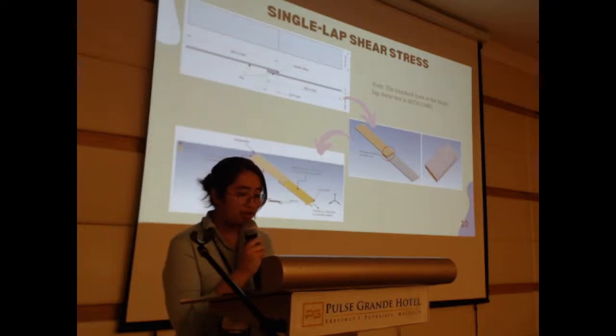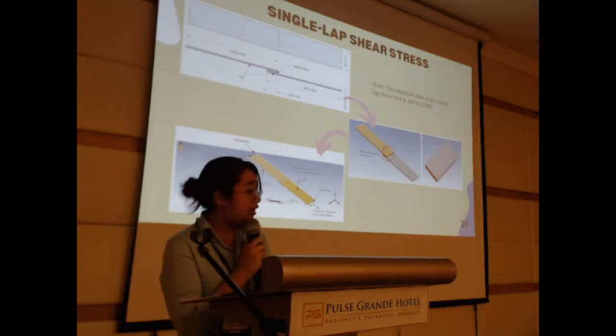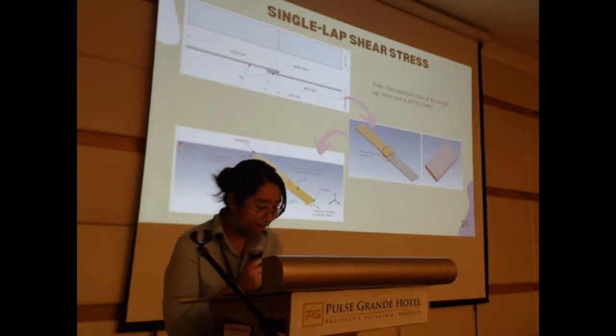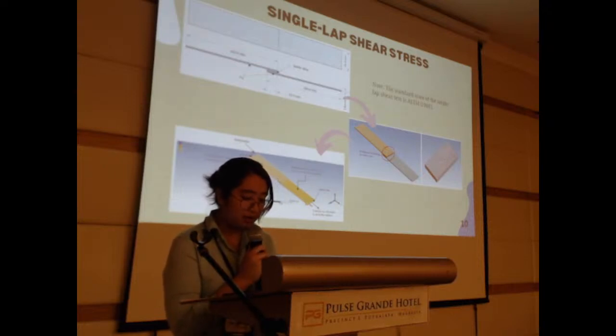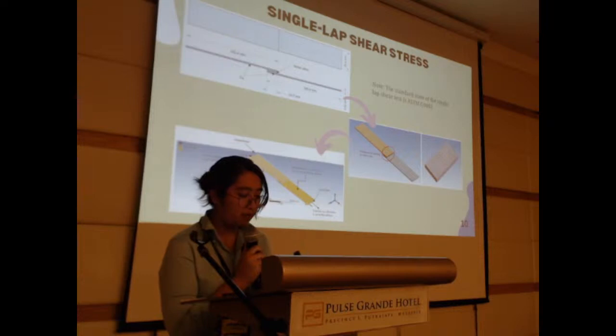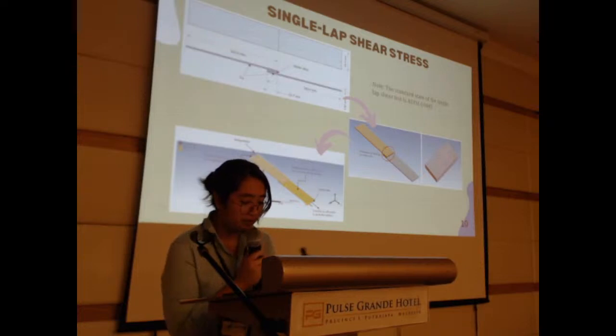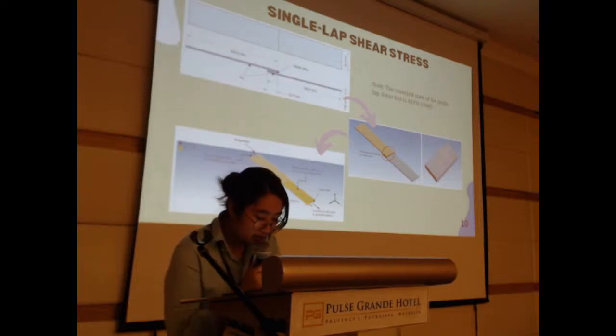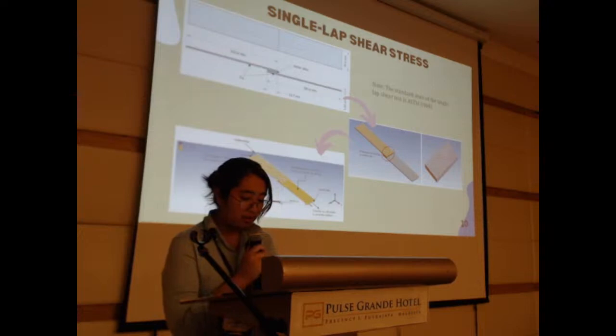Then the geometry will be applied to ANSYS to test the impact of the load applied. So the mesh sizing will be about 3.175 mm, with the refined region employed as hex dominant mesh for higher accuracy simulation results. As you can see below here, one of the metal plates is set to a fixed support on one end of the plate. At the other end of the plate, velocity was applied in the positive x direction to replicate the crosshead speed during the shear test.